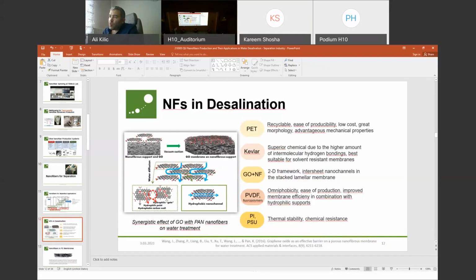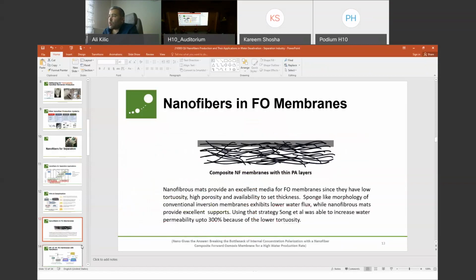So imagine that if you do not use nanofibrous mid layers, you are going to use, for instance, phase inverted membranes here as the mid layer. But these nanofibrous layers do have high porosity, meaning that water can penetrate easily through this mid layer. Otherwise, if you do not use nanofibers, you are going to use maybe a microfiltration membrane under this interfacially polymerized layer. So this is causing a lot of pressure for the water to permeate. So nanofibers, as I said, basically for desalination purposes, we have to concentrate on these mid layers, and if we put something over them, we can enhance the performance to quite larger degrees.